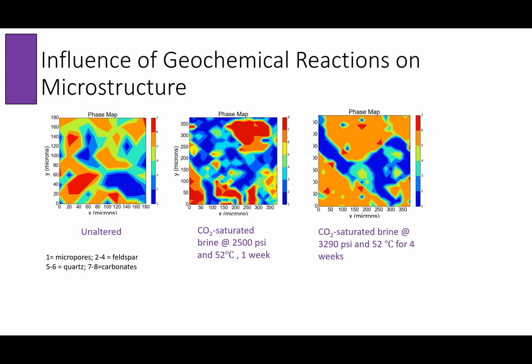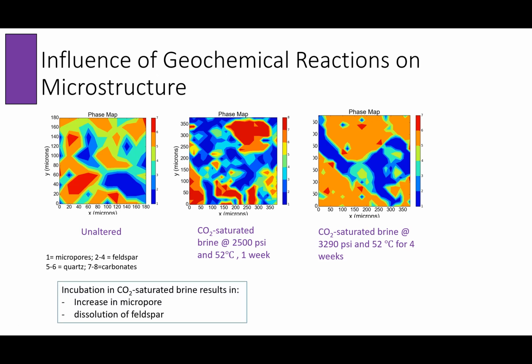And that's very interesting because if you look at the phases, just visually, you understand what's happening. So you have the blue phase. The blue phase represents micropore, and the blue phase is just gaining ground. If you look at the second and the third image, you see more blue compared to the first one. And that's actually one thing that we are observing in the sense that we are increasing the porosity. And then if you look at the light yellow and light green phase, that is receding. The light yellow and light green is linked to feldspar. So we are dissolving feldspar components in this case. So what we are seeing is this increase in micropore and this dissolution in feldspar.